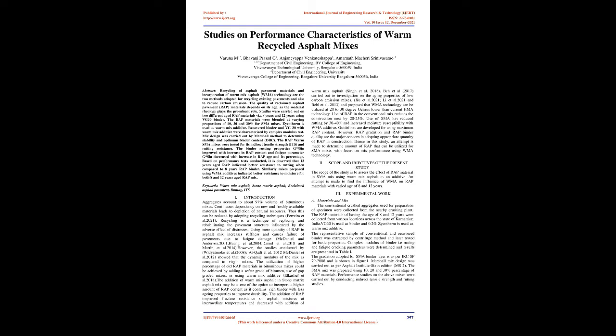The binder rutting property G*/sinδ improved with increase in RAP content, and the fatigue parameter G*sinδ decreased with increase in RAP age and its percentage. Based on performance tests conducted, it is observed that 12 years aged RAP indicated better resistance to rutting when compared to 8 years RAP binder. Similarly, mixes prepared using WMA additives indicated better resistance to moisture for both 8 and 12 years aged RAP mix. Keywords: warm mix asphalt, stone matrix asphalt, reclaimed asphalt pavement, rutting, ITS.